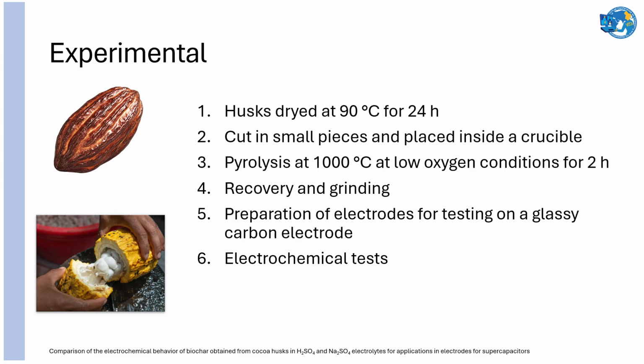To obtain carbon, all traces of pulp and impurities were removed from the cocoa pods, which were then washed with deionized water and ethanol in an ultrasonic bath. The material was then dried in an oven at 90 degrees C for 48 hours. Then, a system of crucible arrangement with silica sand was used to restrict the entry of oxygen into the system. 10 milligrams of dried cocoa pod pieces were placed inside a 30 milliliter alumina crucible, covering the empty spaces with silica sand. After this, a heat treatment was carried out at 1000 degrees C for 2 hours. Finally, the sample was recovered and ground until a fine powder was obtained.